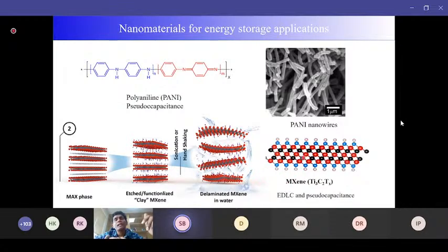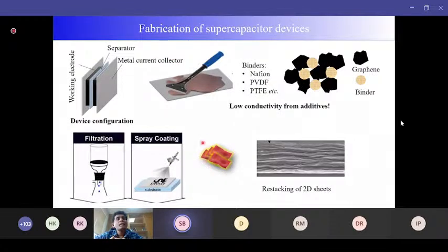Here I have given you one example of the MXene, a titanium carbide based one, the Ti3C2Tx. The Tx denotes that during this exfoliation and chemical treatment, certain functional groups like OH and COOH become attached over the surface, and this gives rise to the water dispersibility of those MXene nanosheets. So the story will be based on the graphene, polyaniline and MXene here. And let me then show you how to construct.